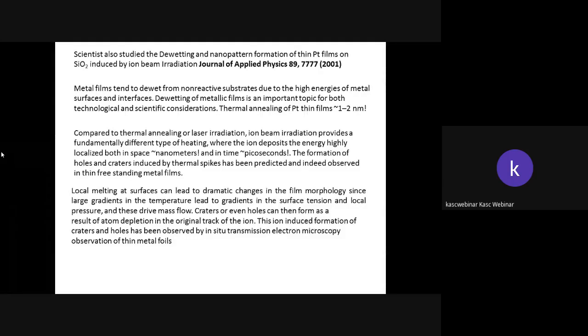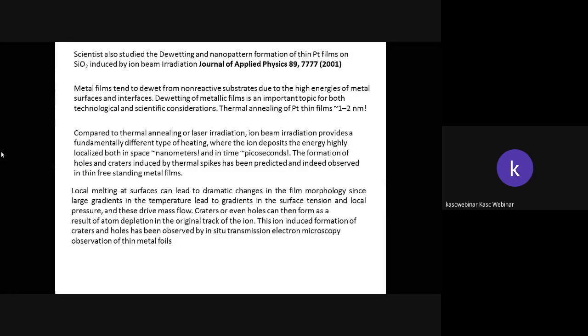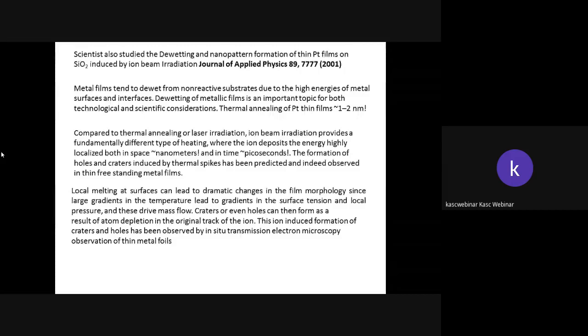Compared to thermal annealing or laser irradiation, ion beam irradiation provides a fundamentally different type of heating, where the ion deposits the energy in a highly localized path in space, especially in nanometers, and in time, within picoseconds. The formation of holes and craters induced by thermal spikes has been predicted and indeed observed in thin freestanding metallic films.